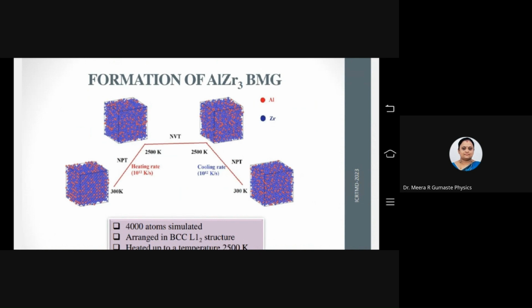The first one, on the left hand side, is at 300 Kelvin. That is the initial structure, which is a BCC L12 structure containing 4,000 atoms of aluminum and zirconium. So it is at room temperature. Then we heated the system from 300 Kelvin to 2,500 Kelvin to melt the crystal.